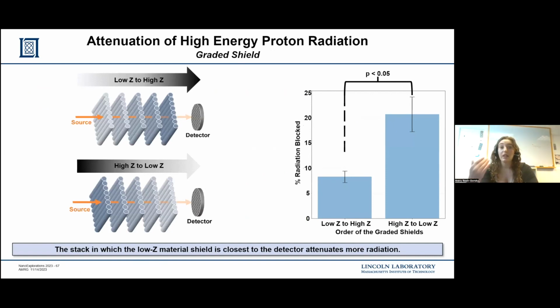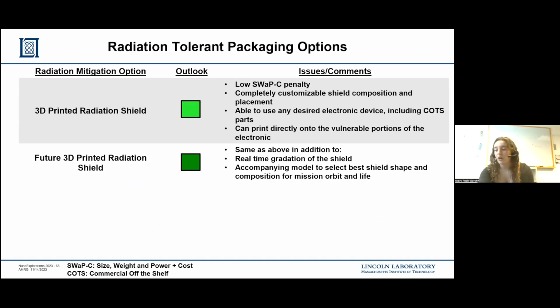Finally, in our proton testing, in order to set the stage for our future work, we wanted to see how the order of our graded shields, like stacking them in front of the detector, affected the percent radiation blocked. So we stacked our shields starting from 100% boron nitride to 100% tungsten, and then vice versa. As you can see from the bar chart, there is a statistically significant difference between the amount of radiation blocked depending on the order. The stacking from high to low Z, so the boron nitride shield is adjacent to the detector, outperforms the other. And this actually is fully supported by literature. This set our stage for our future work.